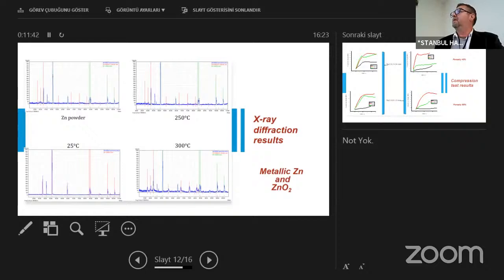After the cold sintering, when we didn't heat the samples and left them at room temperature, we see only the zinc. The zinc oxide with the acetic acid usually forms zinc acetate, which was below the detection limit of our experimental setup, so we couldn't see that. After heating, and after the zinc acetate decomposition, it decomposes in air to zinc oxide, which is there also.